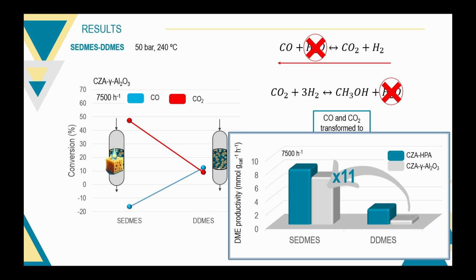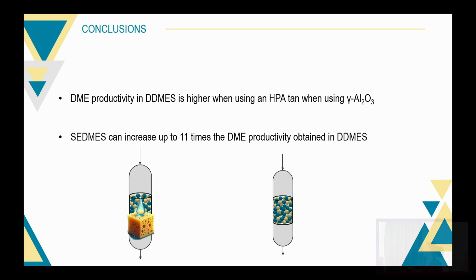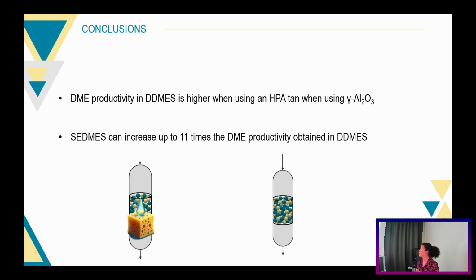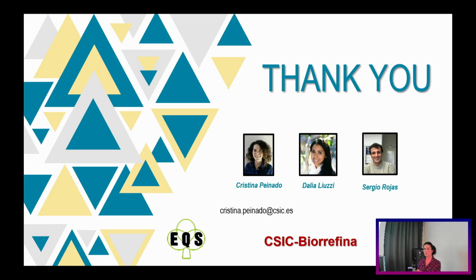So as conclusions, we can say that DME productivity in the direct synthesis of DME is higher when using a heteropolyacid function than a gamma alumina function. And we can also say that SEDMES can increase up to 11 times the DME productivity obtained in the direct synthesis of DME. So thank you very much for your attention.